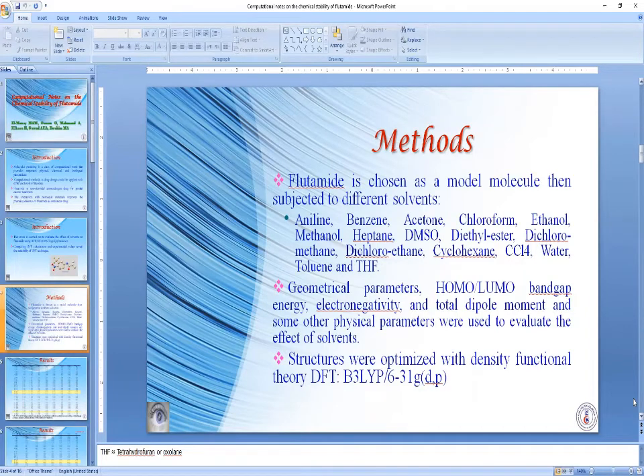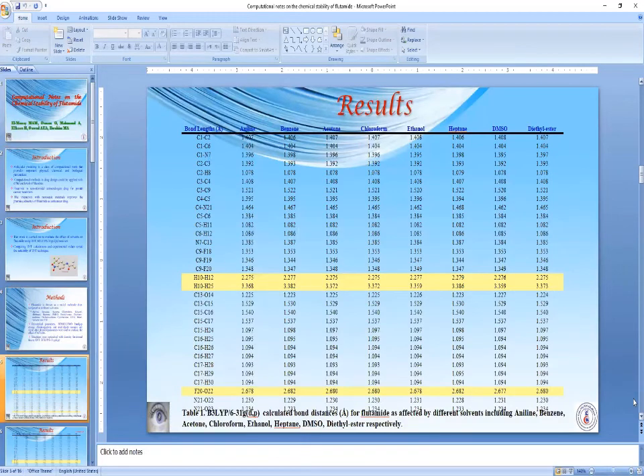The calculations were performed by placing the solute in a cavity within the solvent using the default self-consistent reaction field method. The optimized parameters of solute-solvent interactions have been calculated using DFT B3LYP over the 6-31G basis set. As we can see, remarkable interactions have been detected.